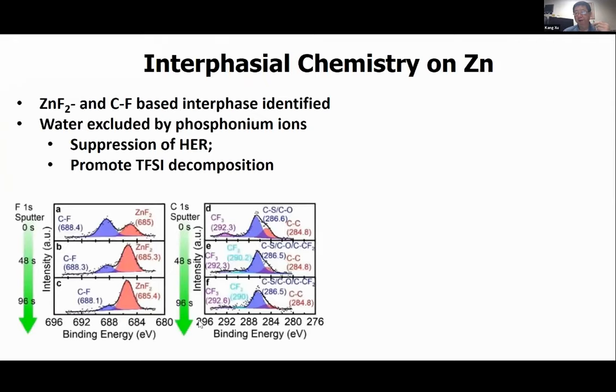Upon cycling of the cell and opening up the cell for post-mortem analysis, we found very definite proof that an SEI formed. This conflicts with the traditional wisdom that zinc cation cannot pass through the SEI. We found that this SEI has a rich content of fluorine, which has both zinc fluoride and carbon-fluorine species. Those can only come from one source, that's the TFSI anion.